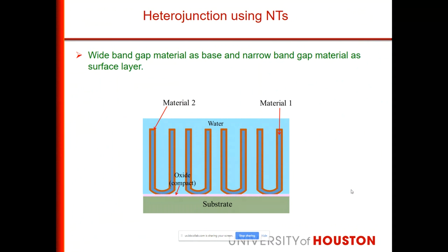Very recently we changed the strategy from doping. Doping had its own problems, so we changed the strategy. Now what we work on is coating the titanium dioxide with very thin two-dimensional materials, so they can absorb light and transfer the charge to the titanium dioxide nanotube. That way we can use a very inexpensive light absorbing material. For example, rust, Fe2O3, iron oxide, can be used as a 2D material. If we can make a 2D material of iron oxide, we can coat the titanium dioxide nanotube with that very cheap rust and generate fuel out of that.